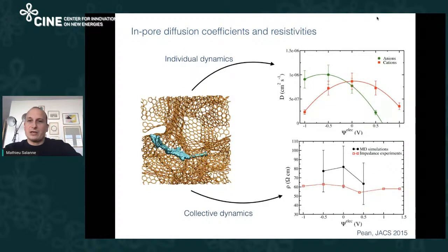So you see that they are of the order of magnitude of 10 to the power -6. And in fact, this is 10 times slower than in the liquid. So dynamics is slower, but it's still high enough to allow fast charging of the supercapacitors. And so this is a very important result, because indeed it means that this nanoporous carbon can be useful in commercial applications.